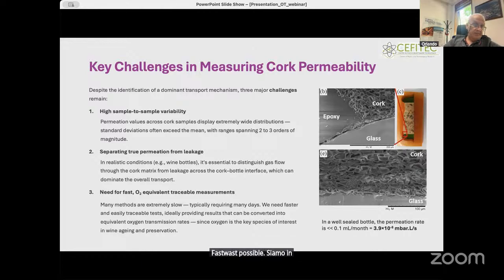Some of these measurements may take months to get. And so we believe we found, we refined, a technique to do it in a few hours or a few days eventually, but we could be sensitive and reproducible with cork.